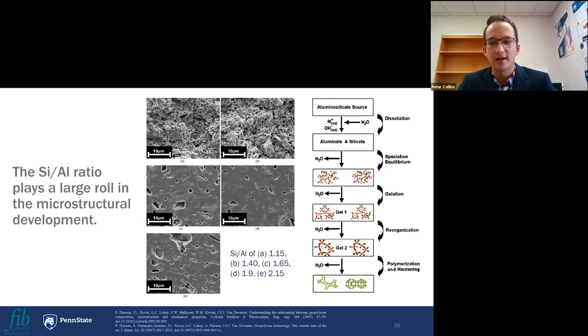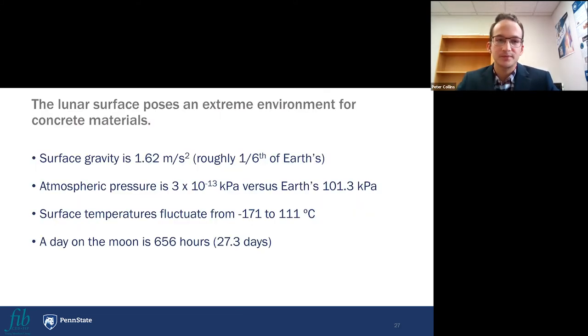You can see the higher the silica to alumina ratio, you get a smoother structure in comparison to some of the lower ones at like 1.15 to 1.4. Luckily, most of the lunar soil is at least in the 1.6 and above region for the silica to alumina ratio. So we get these nice smooth structures in comparison to something that was a bit lower.